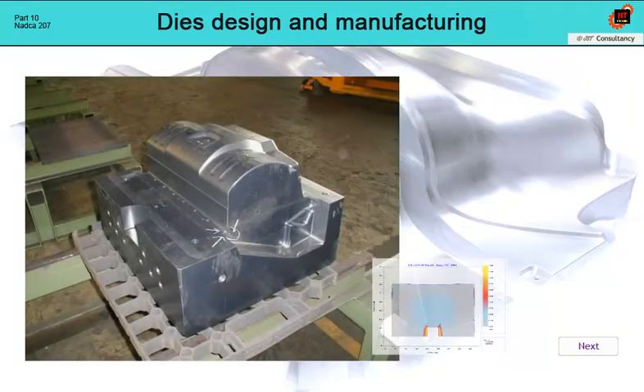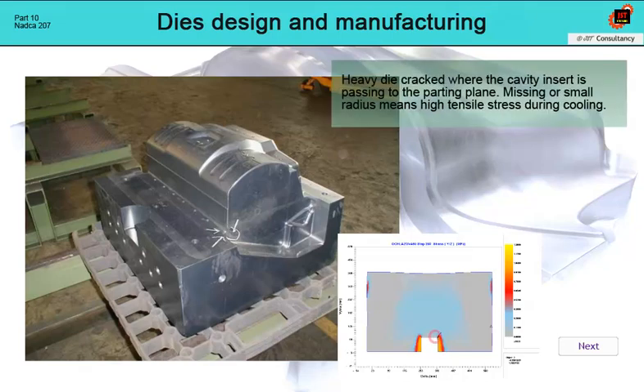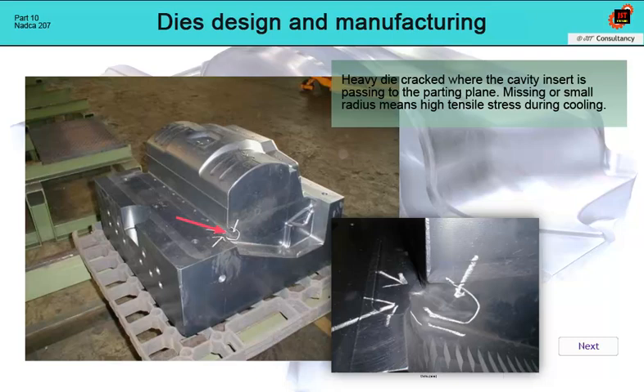This image shows an example from Kind & Company, where a heavy die cracked where the cavity insert is passing to the parting plane. Missing or small radius means high tensile stress during cooling. It is with this example that steel supplier Kind & Company shows why the minimum radius should be at least 3 millimeters. However, it must be said that a crack will only occur if the maximum tensile stress exceeds the strength limit of the material. So, there is a clear relationship between quality die design and quality steel.